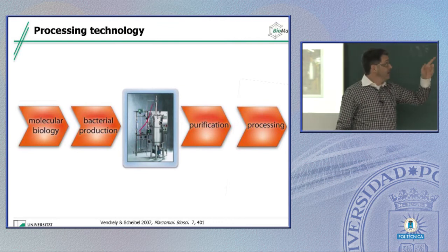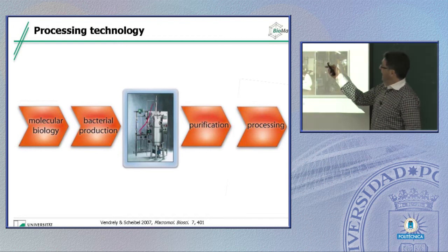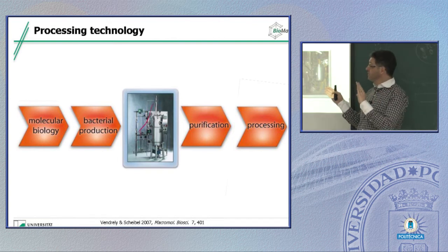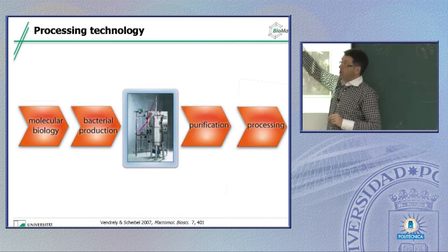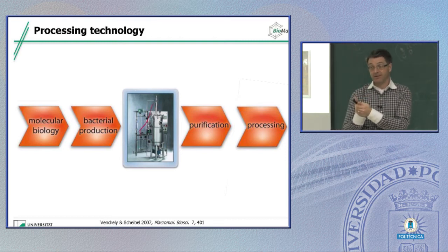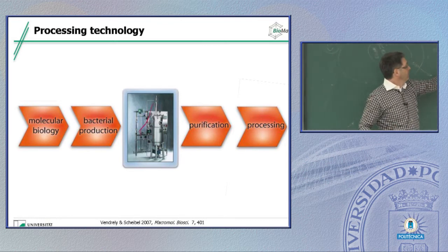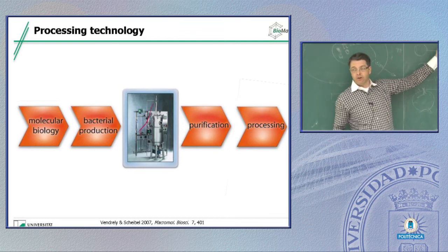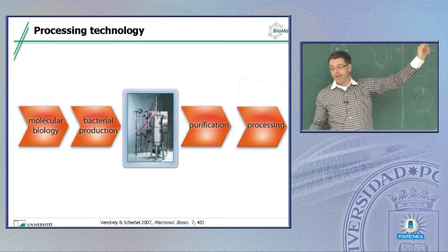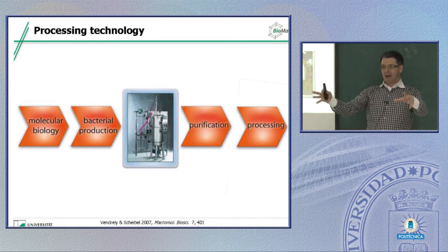So what you have to do is to get that stuff out. Then it has to get clean. That's what we call purification. And there are of course 2 different means of getting proteins purified. One is for technical applications, and the other one is for biomedical applications. Why is that a difference? Well, for technical applications, what you do, you mechanically crack open the cell wall just with shear forces, so everything comes out. And then you separate anything that's insoluble. In the lab, that's easy. You have a centrifuge.